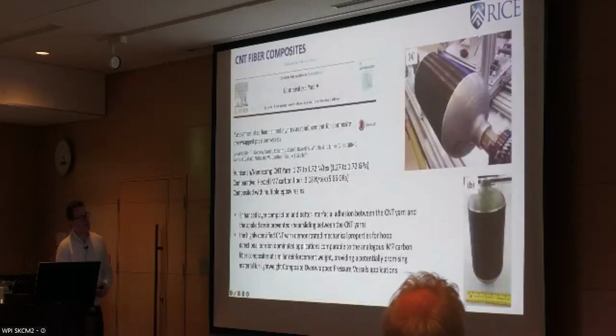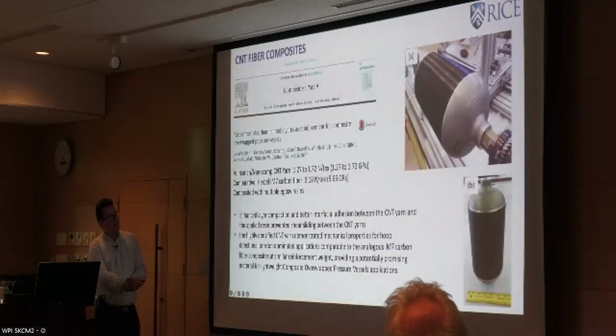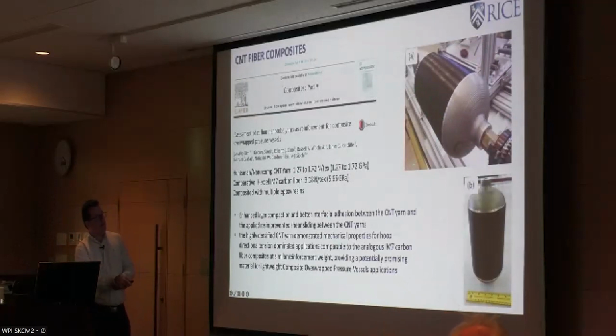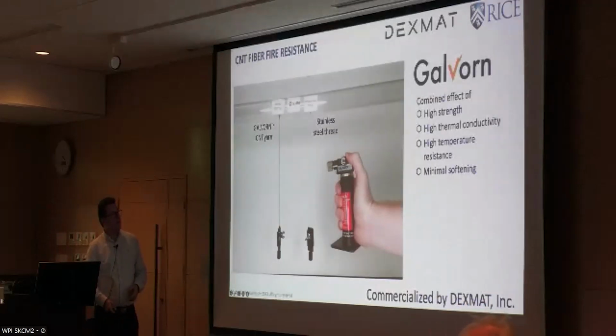There's also some surprising things that come from the high surface area. This is NASA, who's made, this is not my work, it's work done by NASA with a company called Nanotubes, pressure vessels for hydrogen storage. Normally, these are made with carbon fibers, so high strength carbon fibers. So you see these carbon nanotube fibers were about half of the tenacity and about a third of the strength of the carbon fibers. However, when they were put together in a composite to make the tank, they actually behave better.